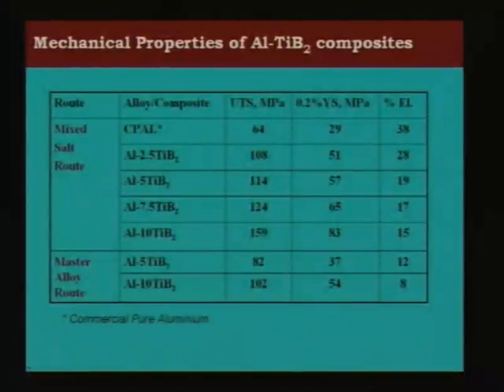So that's why you can see that in most of the composites, particularly those in-situ composites, the ductility levels are very low. That's because of that. Here you can see the ductility levels are still higher. But one thing is that the master alloy route does not promise you that much high strengths, basically because the temperatures at which these are made are very high. At those high temperatures, 1000 degrees or so, you have to go, so that both these master alloys, when you try to remelt, they melt together and give you the reaction.